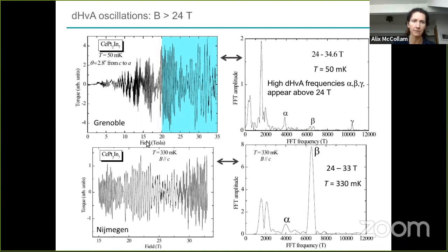This is a comparison of the data in Nijmegen and Grenoble. So it's the same. This is a much higher temperature, so the resolution is worse. But these frequencies, this one is actually there if you zoom in, but these frequencies are still observed, and the splitting is observed in both sets of measurements on both sets of samples.